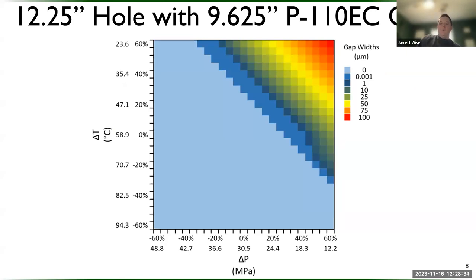So we took a well in the Gulf of Mexico. We pulled all of the drilling reports, the production history, everything from it, and replicated it with our models, after validating and verifying them, of course. We see that cement debonding to the casing is by far the most common failure mechanism. And it's due to either temperature cycles or pressure cycles.